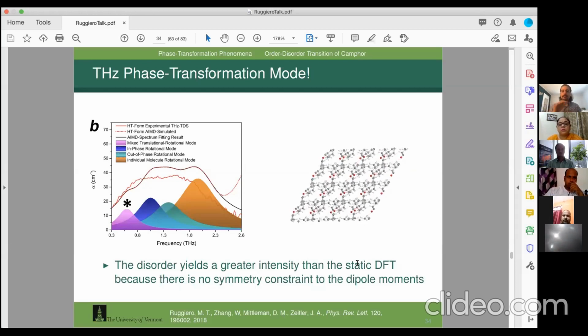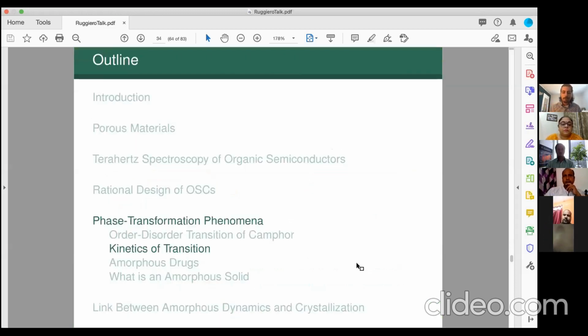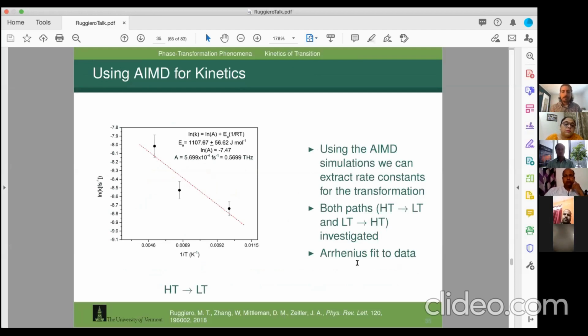It also turns out this vibration is the phase transition mode. So we could do a simulation at different temperatures, fit an Arrhenius plot to it, and work out the activation energy for the transition. But we could also work out this pre-exponential, this A term, which is a collision frequency.